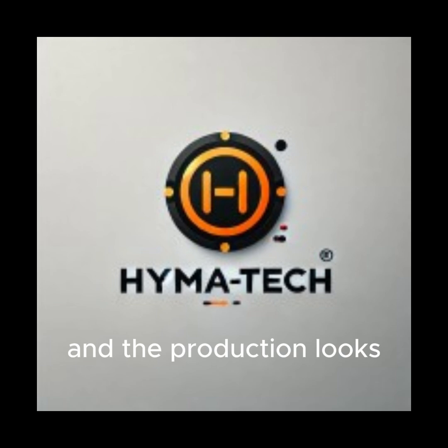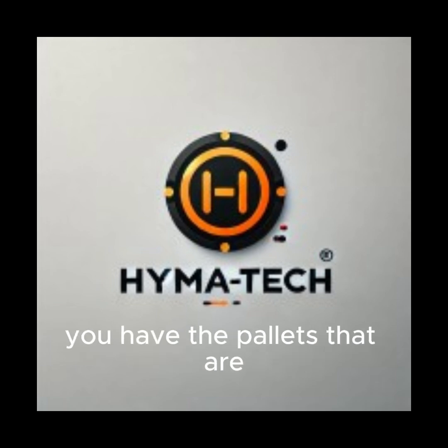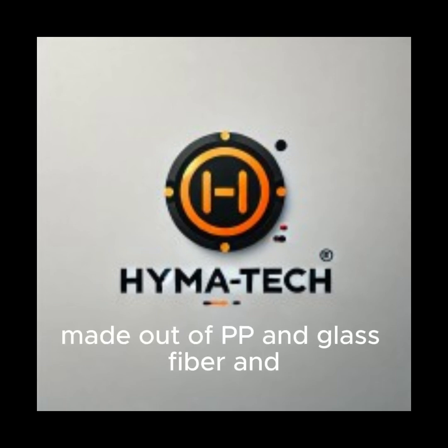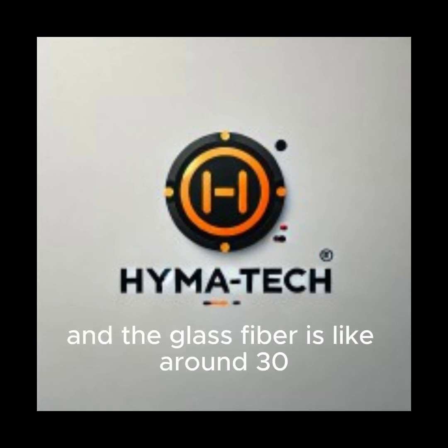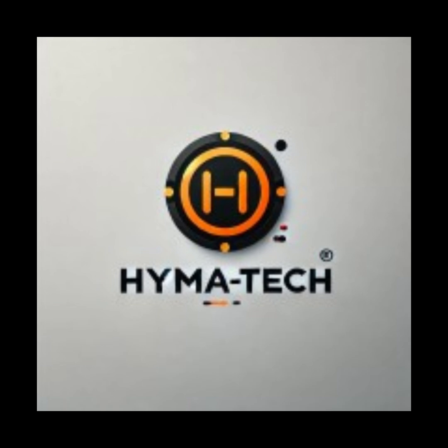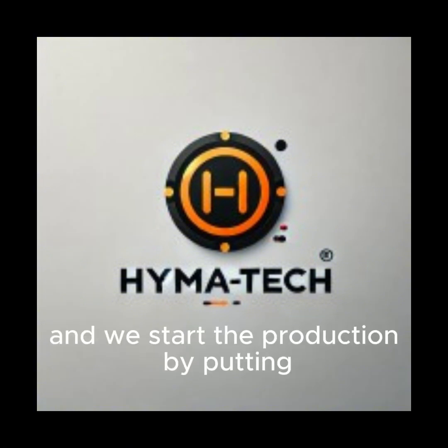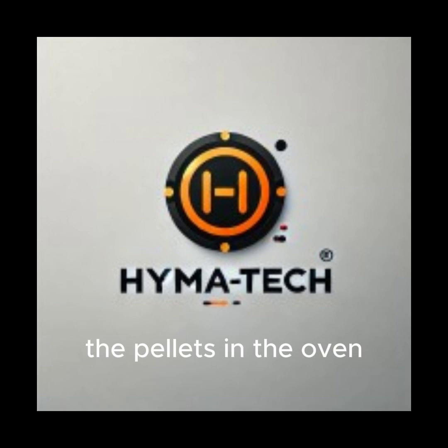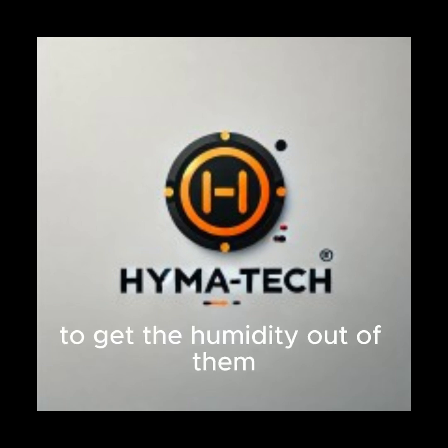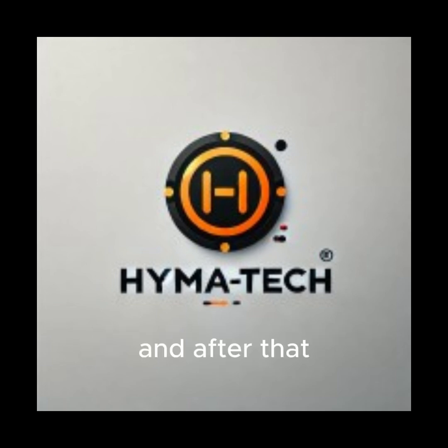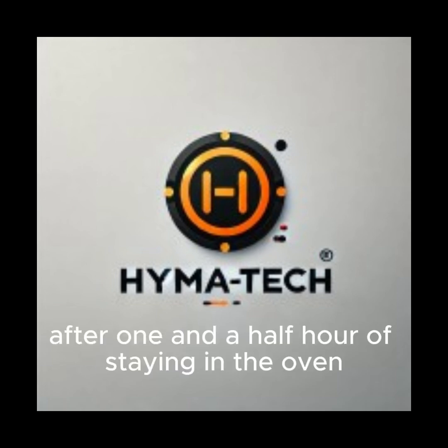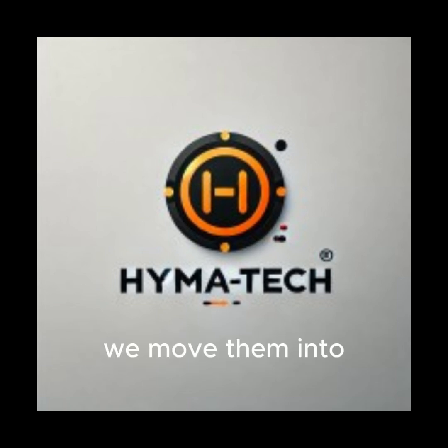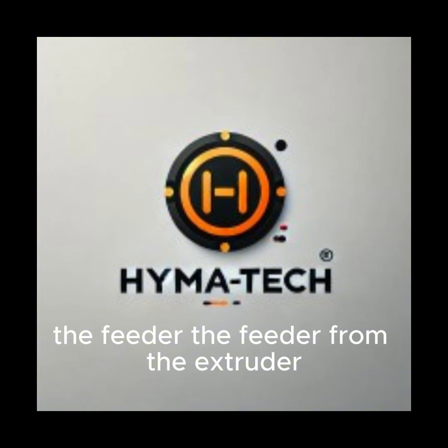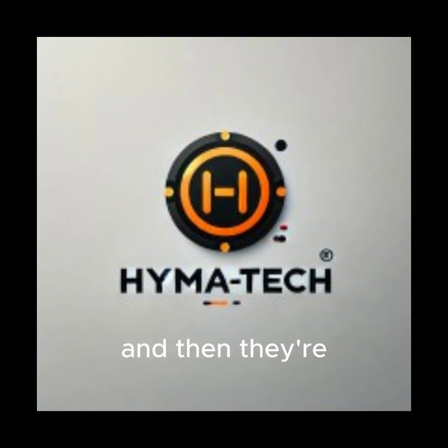And the production looks something like this: you have the pellets that are made out of PP and glass fiber, and the glass fiber is around 30% fiber volume. We start the production by putting the pellets in the oven to get the humidity out of them. After 1.5 hours in the oven at 110 degrees, we move them into the feeder of the extruder, and then they pass through 3 stages of the extruder.